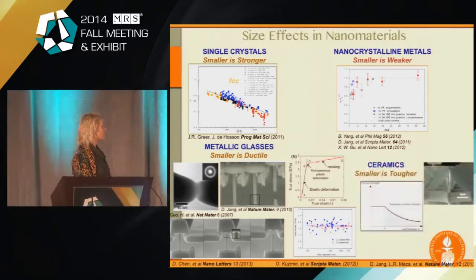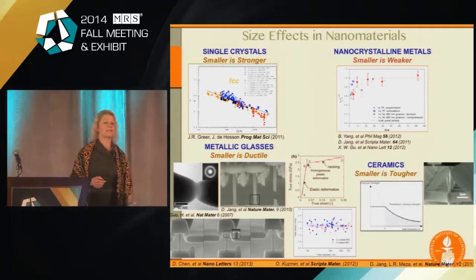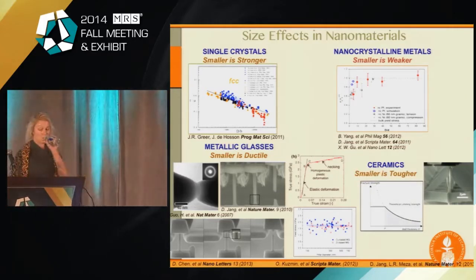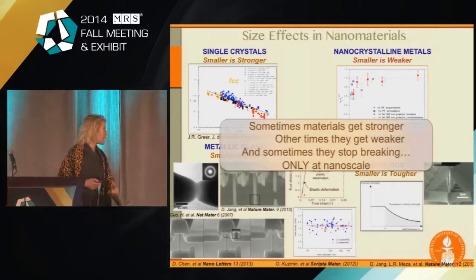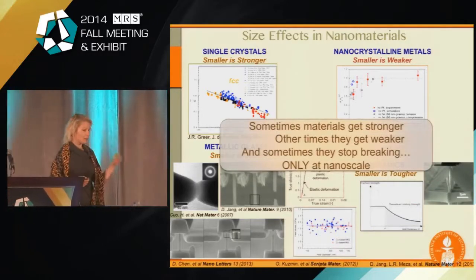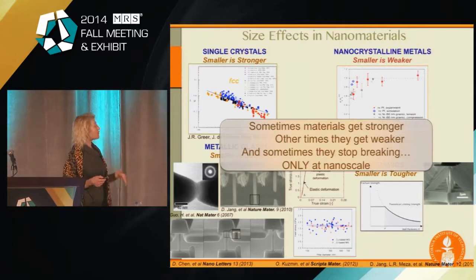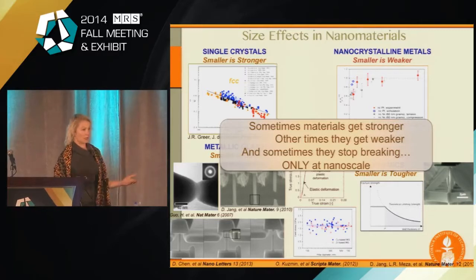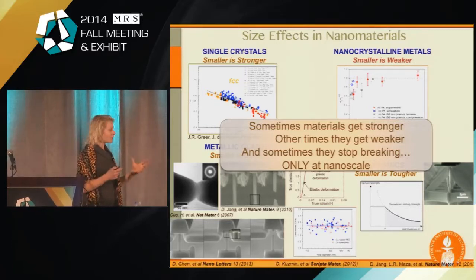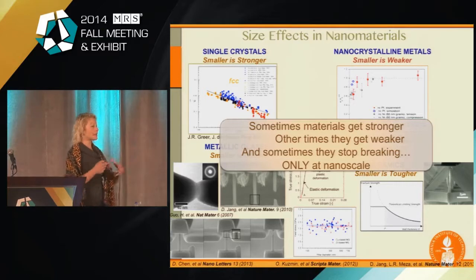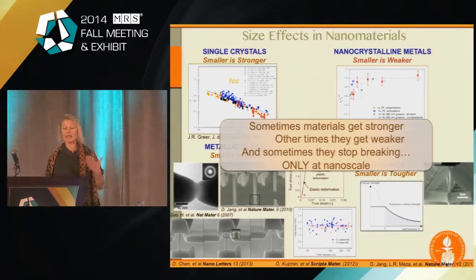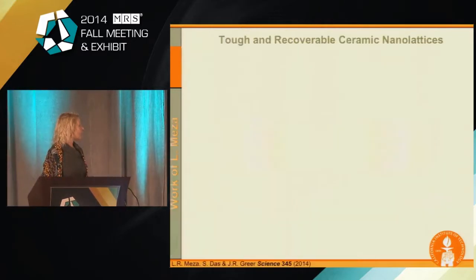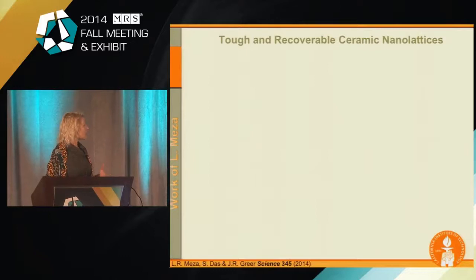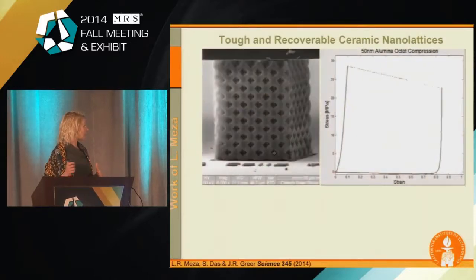Now, in the case of ceramics, we also showed that smaller can be tougher, and what that means is that smaller can be harder to break. So the bottom line here is this. Sometimes materials can get stronger. Some other times they get weaker, and sometimes they stop breaking. But these effects only emerge at the nanoscale. And so this is why it's very important that we make the nanolattices as opposed to the microlattices, so that we're able to harness maybe the size effect. This is something that we're calling the material size effect, and proliferate it onto the larger scale. So just to demonstrate this effect, I'd like to show you this video.